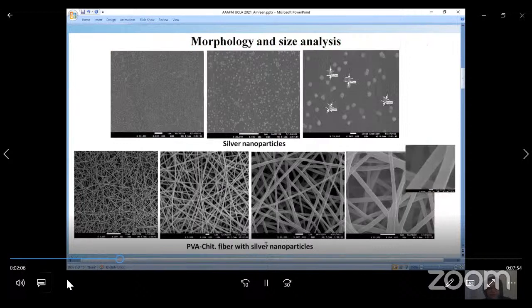For the characterization, we first opted for scanning electron microscopy to confirm the silver nanoparticle and PVA chitosan fibrous formation, wherein the spherical structure of the AgNPs confirmed their morphology, and the size was roughly estimated to be around 60 nanometers, whereas the fibers incorporating the nanoparticles showed a morphology and width of 200 to 300 nanometers.